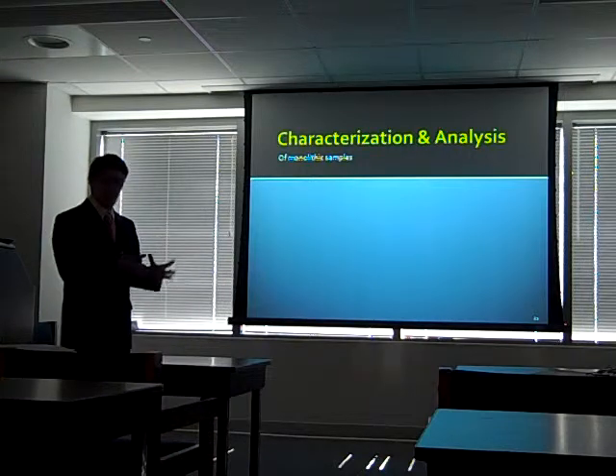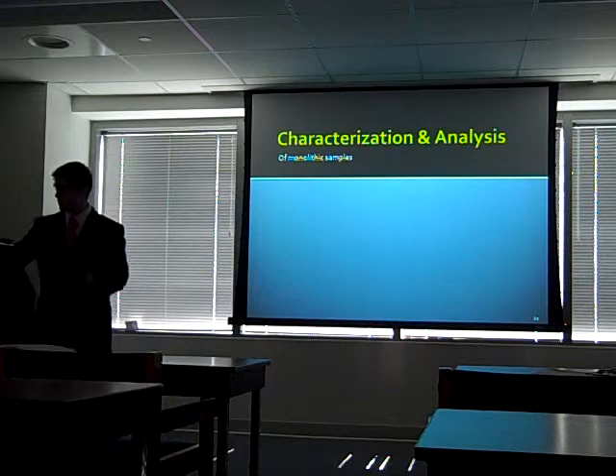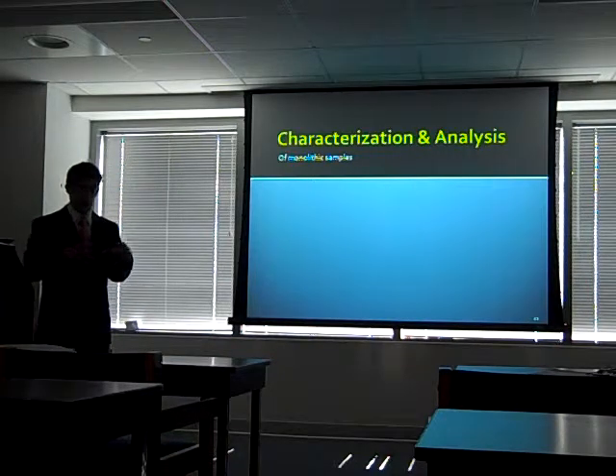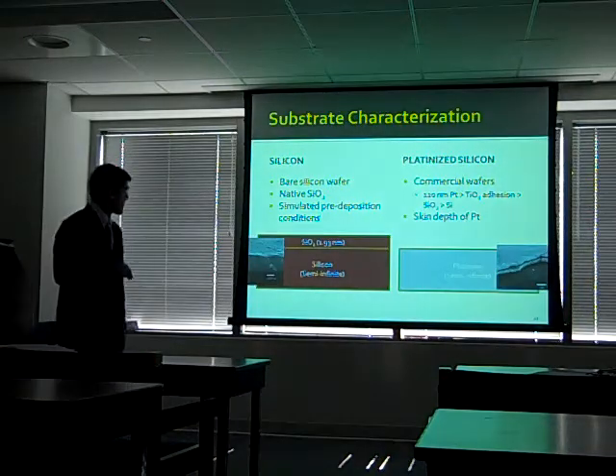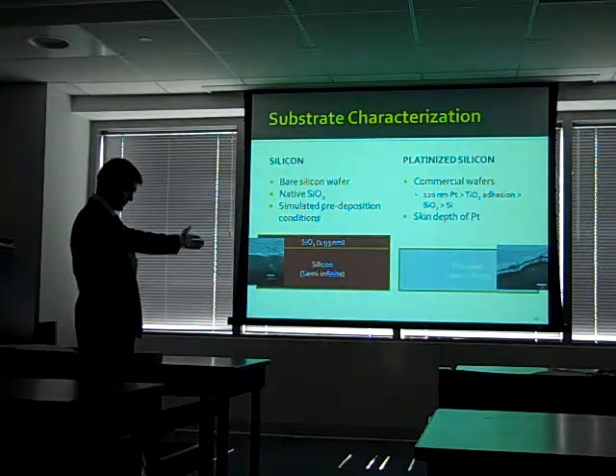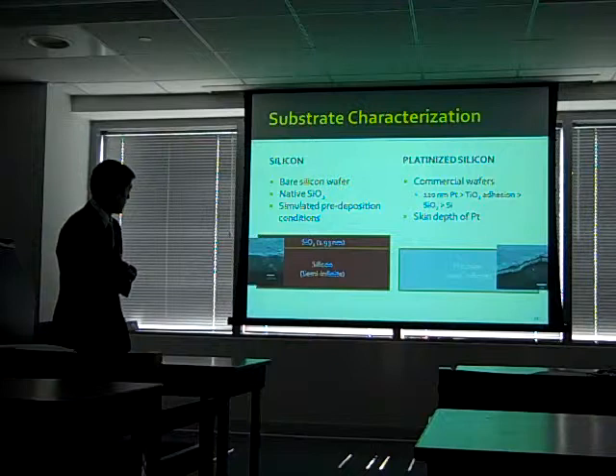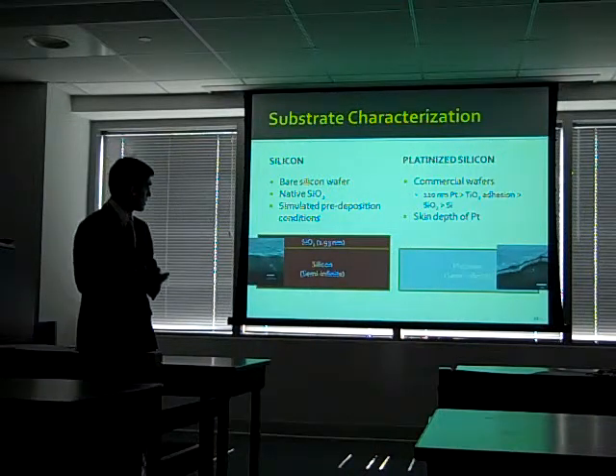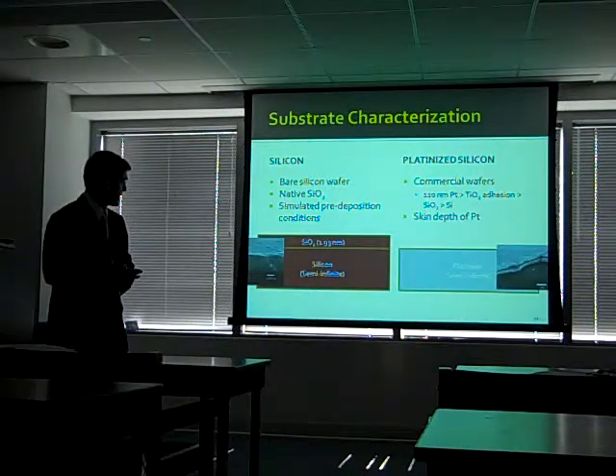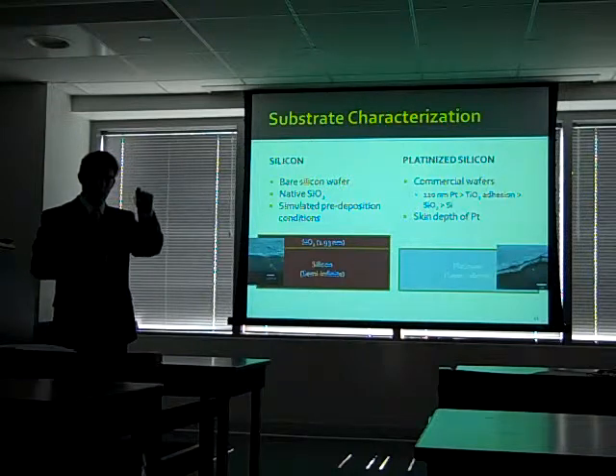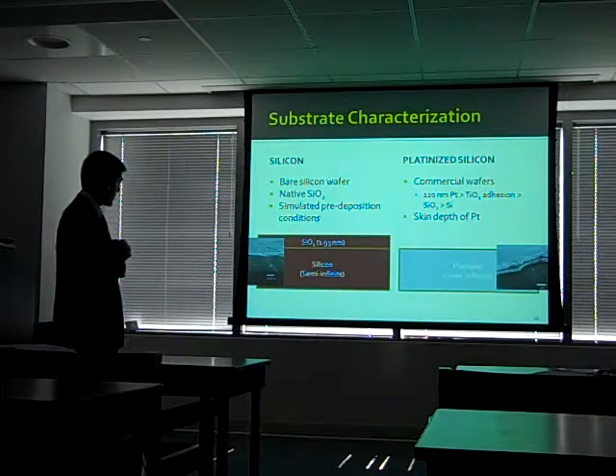Okay, so we know now that we need a computer model to use the VASE technique to learn about our samples. So the first step is to characterize the samples to be able to build this model. I started off with my substrates. The silicon is best modeled as simply a 2 nanometer layer of silicon dioxide on top of silicon.